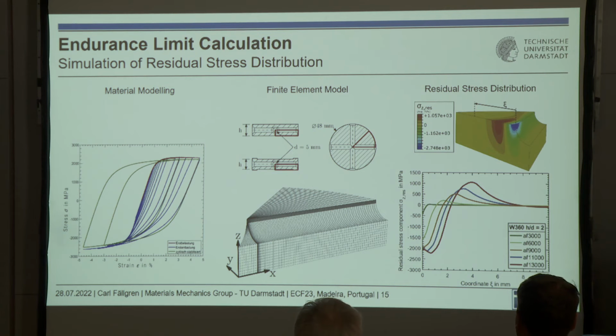So how do we do that? We made some material modeling. We tried different approaches, but now I'm going to show you what we used, a Chaboche model. What we have here in red is the initial loading curve, and what we see in blue are all the initial unloading curves for the hysteresis loops we obtained from our cyclic testing. And in green you see cyclically stabilized loops, and we use the Chaboche model to generate 3 sets of parameters, one for the initial loading curve, one for the initial unloading curve, just to describe the autofrettage pressure, and then afterwards we cycled.